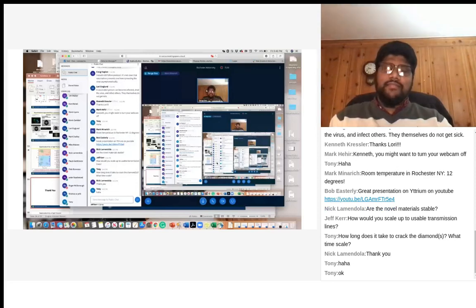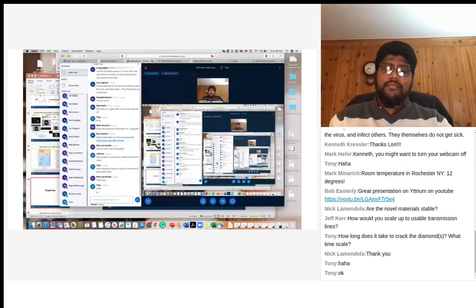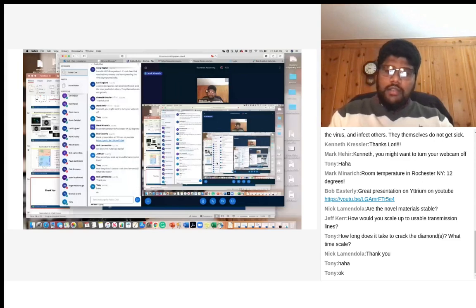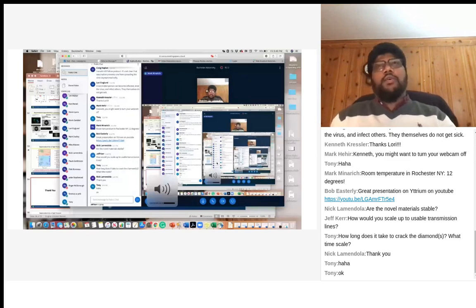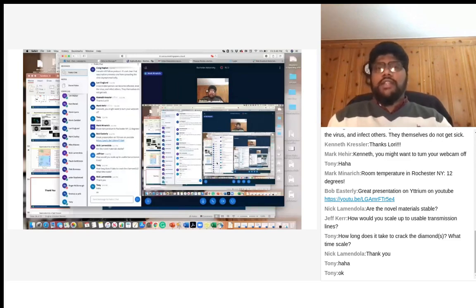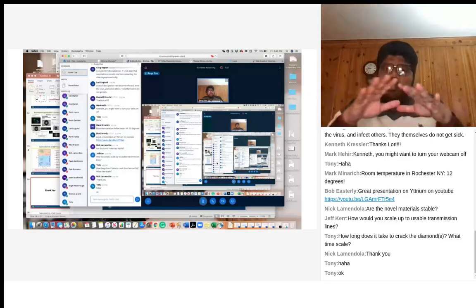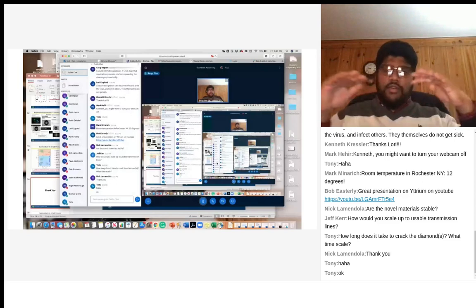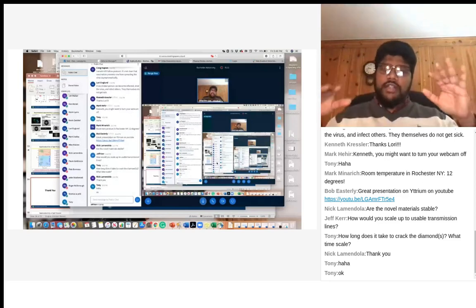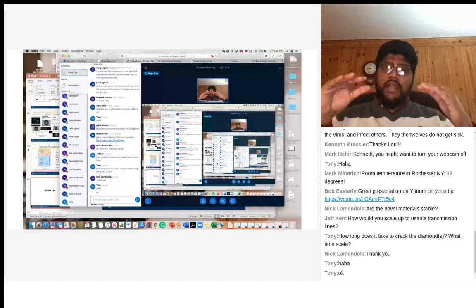So to follow up on Tony's question, if you were to grow your own diamond where you could be a little more sure of the crystal lattice being more uniform, would that, like a more perfect diamond, be a better way to go? Perfect diamonds, we are actually using a synthetic diamond in our lab for this experiment. But the problem is that it's not just about being a perfect diamond. Even though we polish this diamond, the orientation we need, we cut them to the 100 direction, and then we polish this diamond.